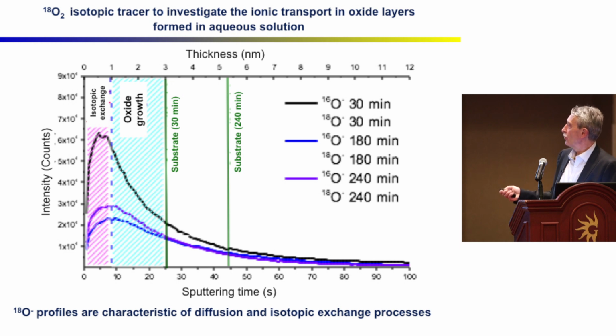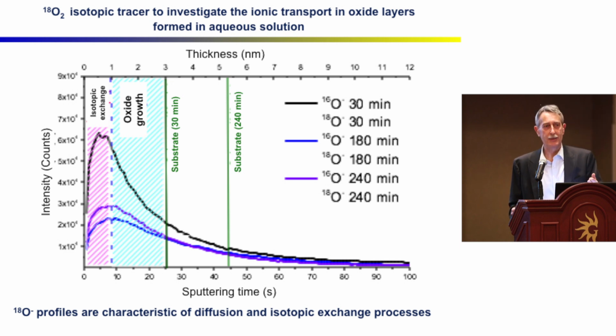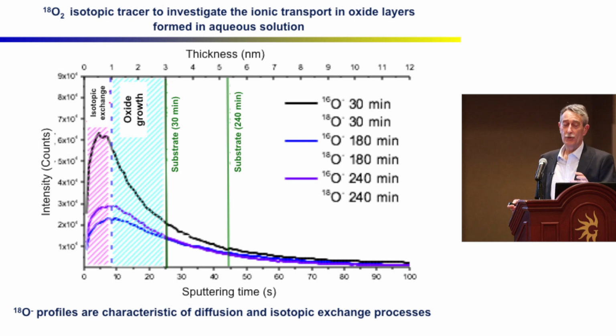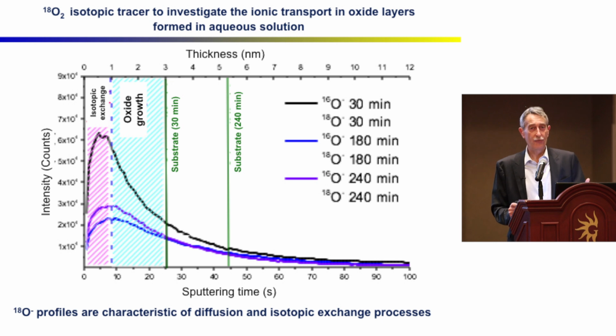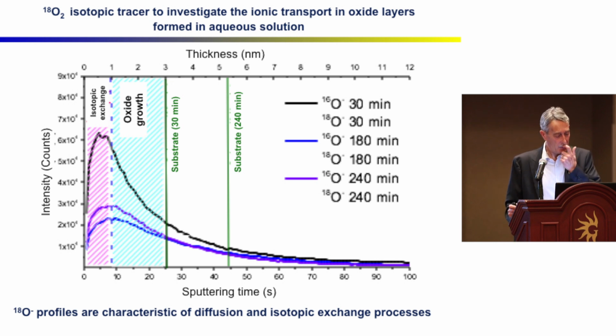Okay. Now we can look at numbers, so we can look in detail at the oxygen profiles. I'm not going to go into the details, but I would like to draw your attention to the fact that there is a slight complication here. These profiles, this is oxygen 16, sorry, and this is oxygen 18, and this is for another exposure time. So let's disregard that. But you see that these profiles are not straightforward to interpret. And the reason is that you have not only solid state diffusion of oxygen or oxygen vacancies, but of course you have also isotopic exchange.